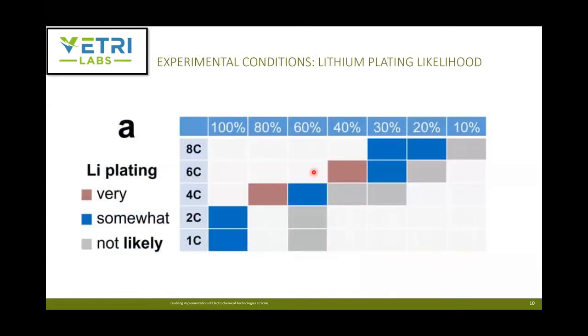Okay. So based on their earlier studies using reference electrodes, they mapped out the likelihood of lithium plating. Here is the rate of charging, 1C all the way to 8C, and then the SOC, 100% to 10%. So we looked at the lithium plating. It's very likely, somewhat likely, and not likely with these different colors. As you can see, as you go to high rate and high state of charge, there is a very high likelihood of plating. But when you're at low rate and a higher SOC, it's fine. That's how they mapped it. This is using the reference electrode.